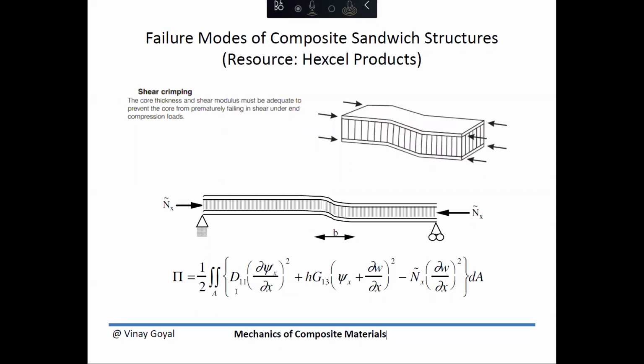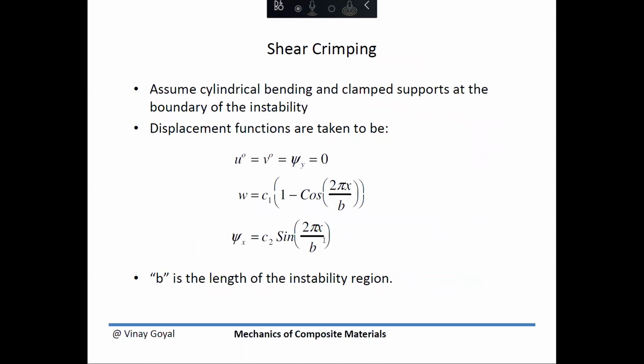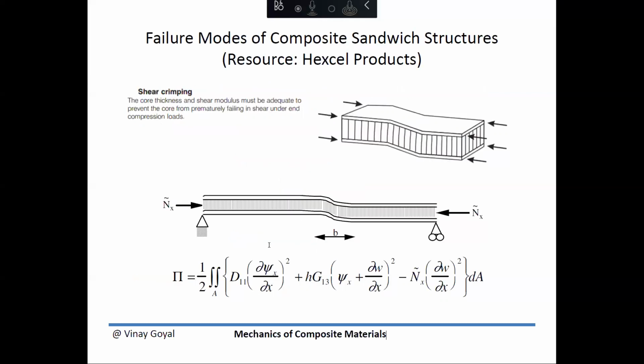Failure modes of composite sandwich structures continue here. We have the shear crimping situation, and in this case, we want to make sure the core thickness and shear modulus are adequate enough to prevent the core from failing in a shear type failure mode. In this manner, if I apply compression loading, suddenly you can have this crimping instability. The shear crimping instability can also be analyzed by selecting deflection assumptions of how it may deform. And here is an assumption that people have taken in the past.